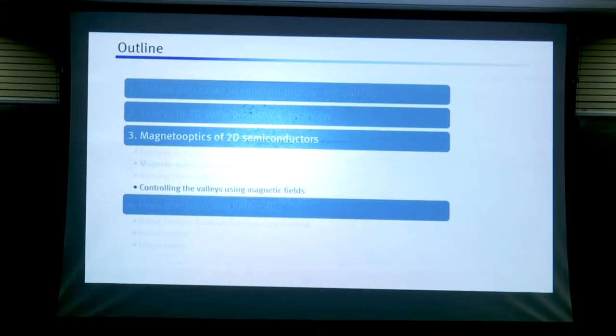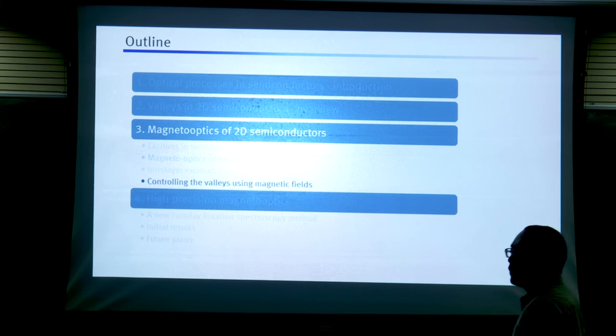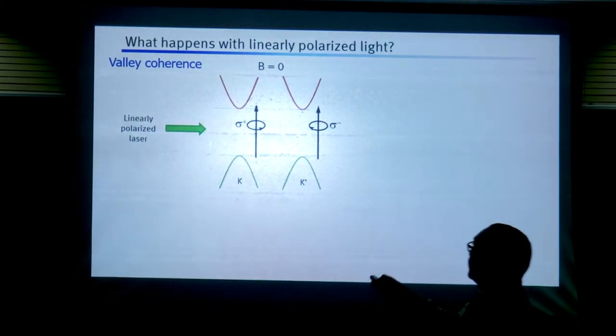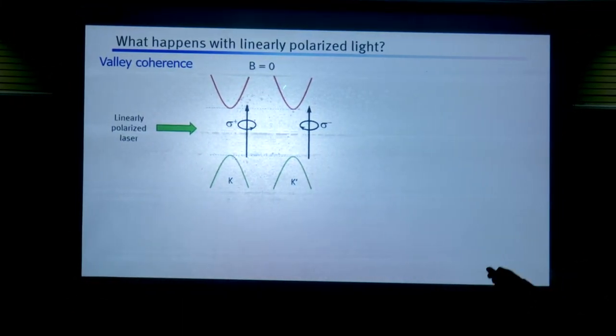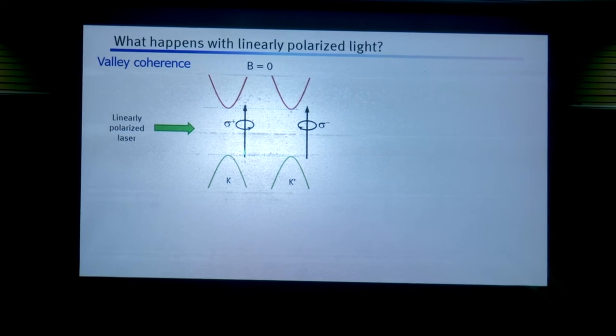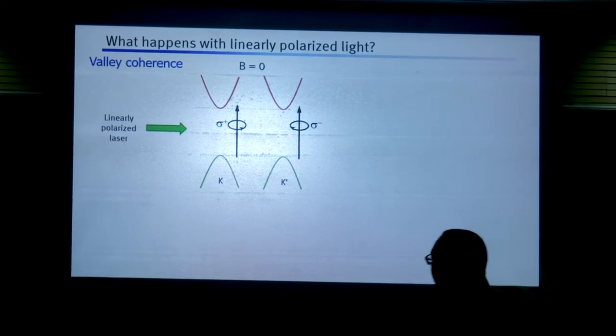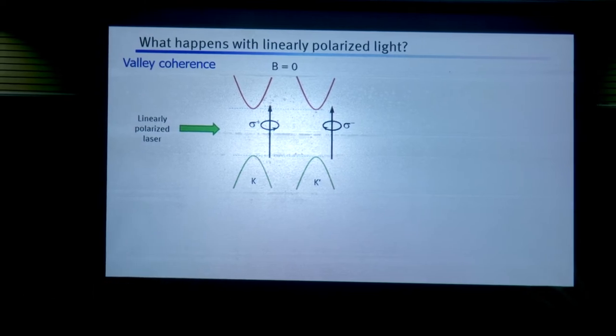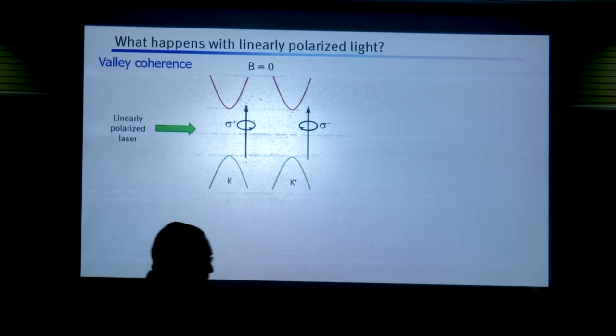Now I claim that actually we can control the phase between these valleys as well. I'll show you one experiment, which was one of my favorite ones. We can control the phase using magnetic fields. What I mean is the following. We have two valleys, both of them coupled with circularly polarized light. Now, if we are able to control the phase between two circular polarizations, then we are approaching closer to the valleytronic gates, which are important for quantum computation.